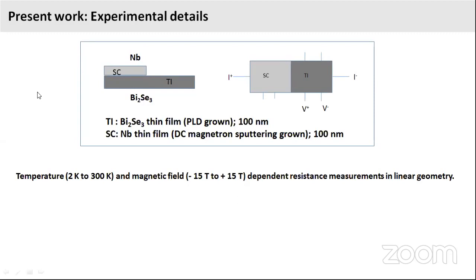is we have deposited roughly 100 nanometers of bismuth selenide using pulsed laser deposition. We partially covered it and deposited a niobium superconductor, which is a type 2 superconductor, using DC magnetron sputtering, which is also 100 nanometers. And we've measured the temperature and magnetic field dependent resistance in linear geometry. So if you notice, current is passing through the entire system and we are measuring voltage across the topological insulator alone, which is not covered by the superconductor, and also on the superconductor, which is sitting on half of the topological insulator. So this is the bilayer and this is the single layer.